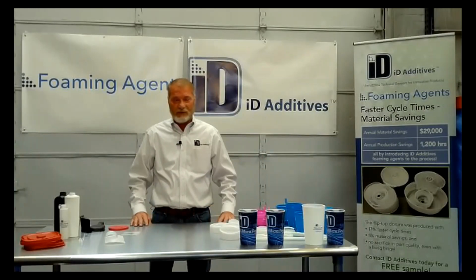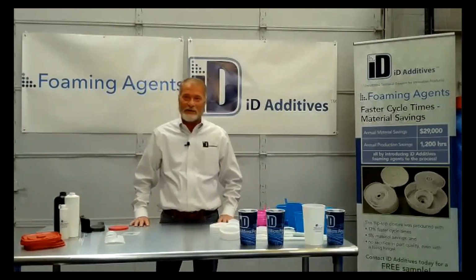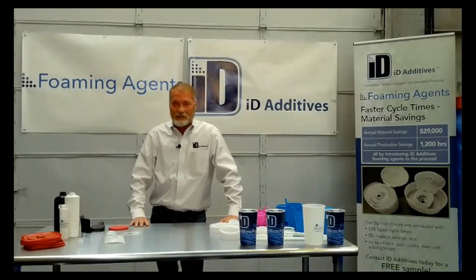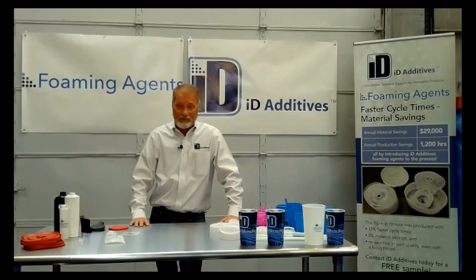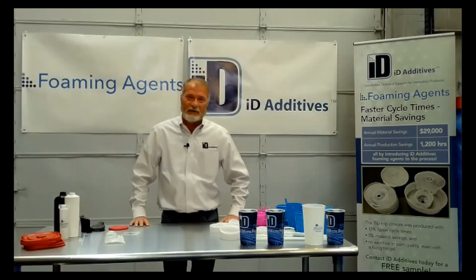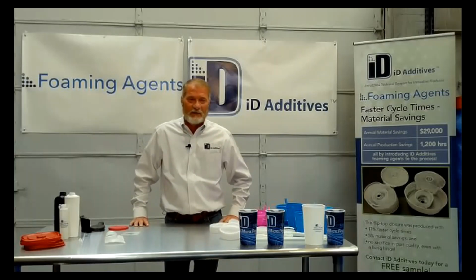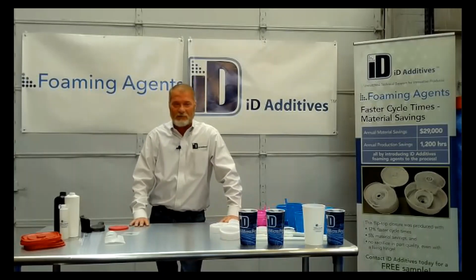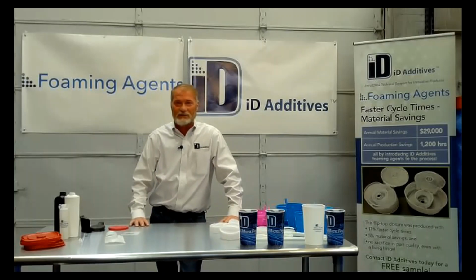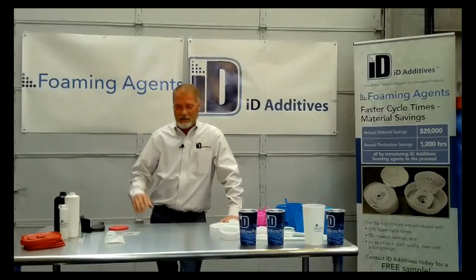Rotational molding, that's pretty much exothermics. They tend to perform better. I've tried it with endothermics. Didn't work very well. Profile extrusion, same. I tried it with endothermics and I learned my lesson with that. Endos don't work. Exothermics work the best. If it's flex PVC extrusion, an endothermic may work. I've had some success with that, but typically if you've got a shape or even pipe, you want to hold that dimension and you want to hold that nice round pipe, you've got to have an exo. That's all there is to it, or a hybrid endo-exo. Either one will work just fine.